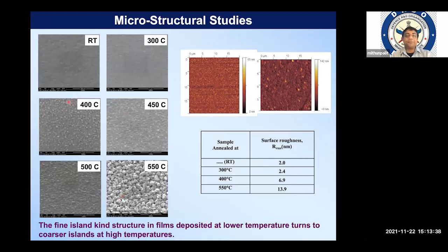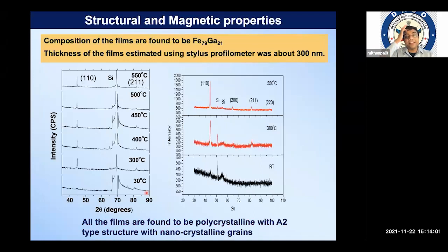You can see at room temperature the contrast is not so much, whereas very island-like contrast you can see, and this is increasing as the temperature is increased. So basically in the fine thin film, the AFM picture also shows the same. And these coarse islands play a very important role in the magnetic domain structure formation in the thin film.